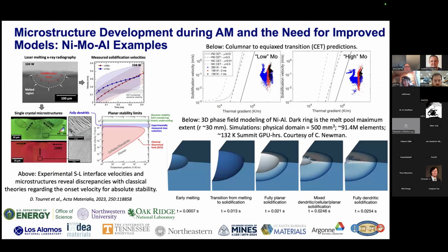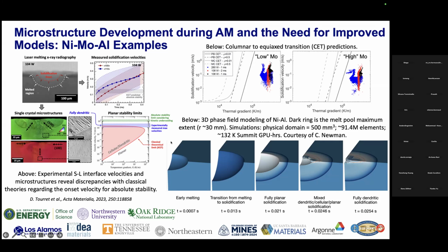And some of the early work that we did, this is an example of those spot melts, two different orientations for a given power condition. And if we look post-mortem, we see from some of our earlier assessments that we actually see dendritic microstructures, even though solidification theory would predict that we were beyond absolute stability. And so we know there's some effects that we need to deal with here in terms of the modeling. And so now that we have a new phase field model, that's a direction we're going in is better modeling of these nickel moly aluminum ternary samples, including perhaps in 3D.